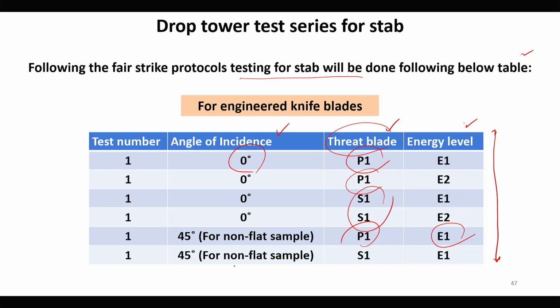For non-flat samples, blade S1 and E1 can be used. And 45 degree will be the maximum angle of incidence for a non-flat sample.